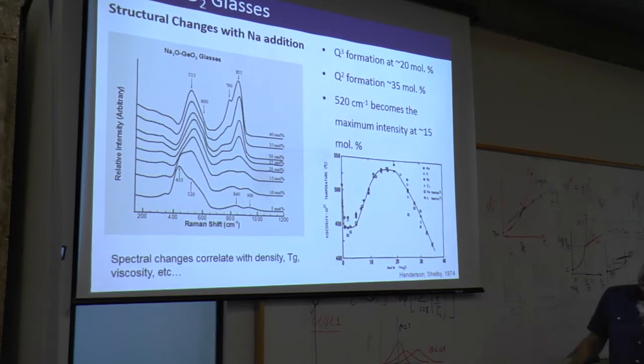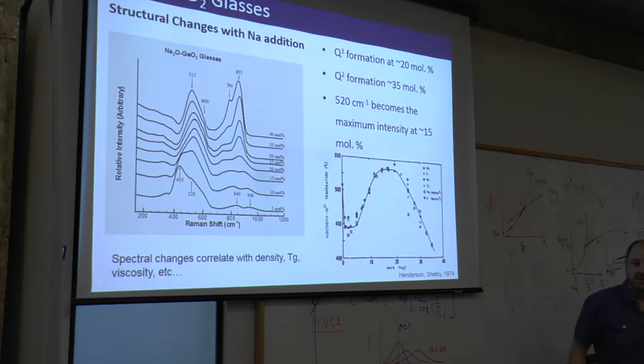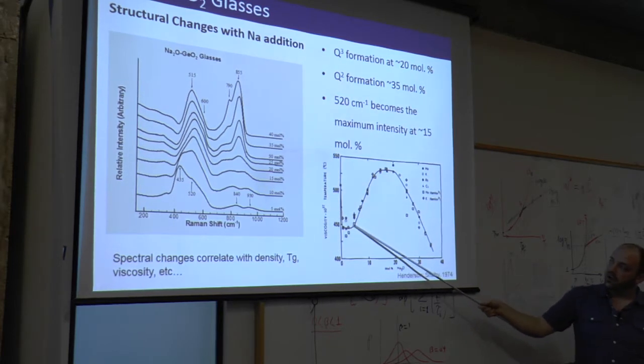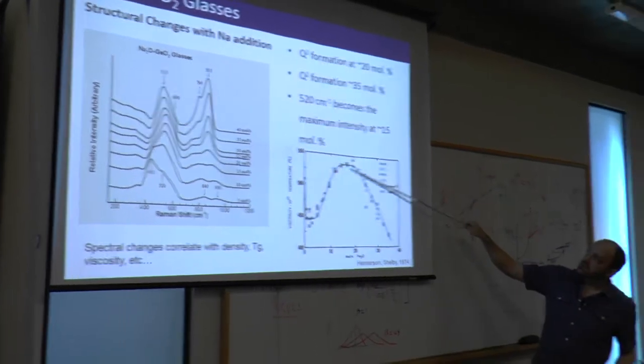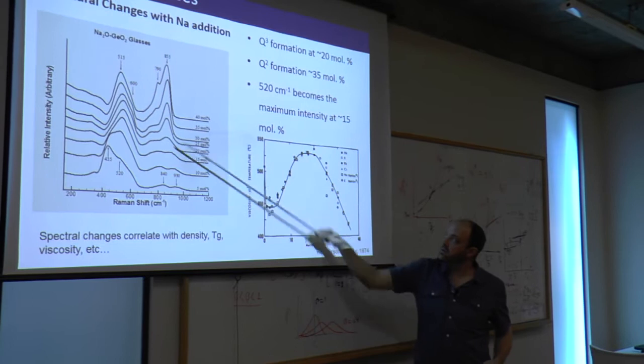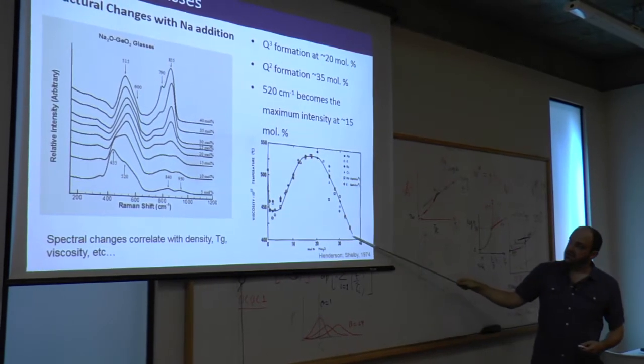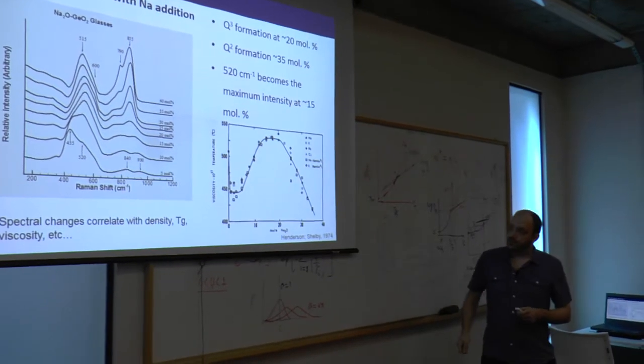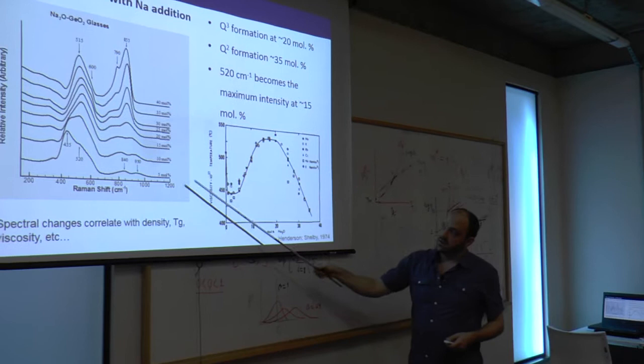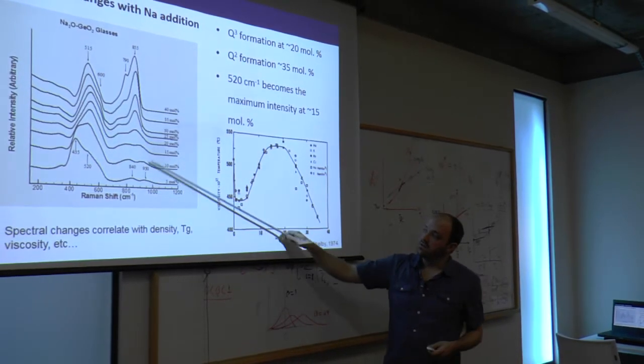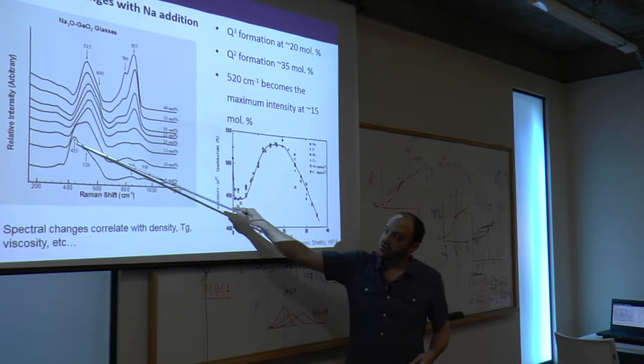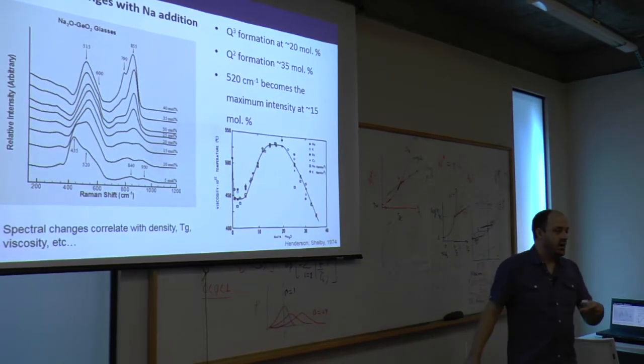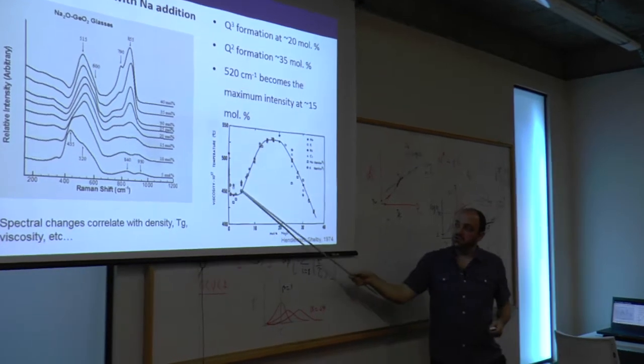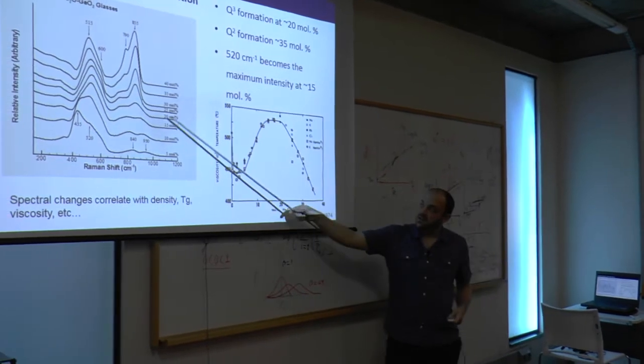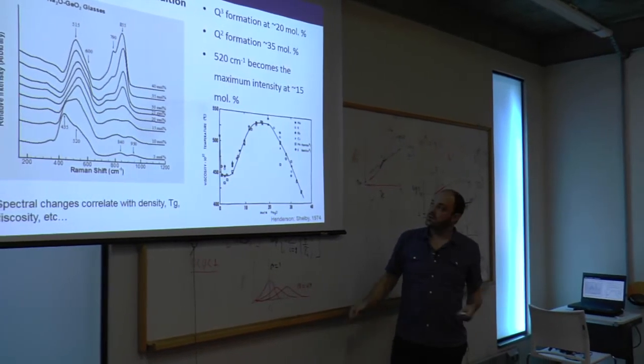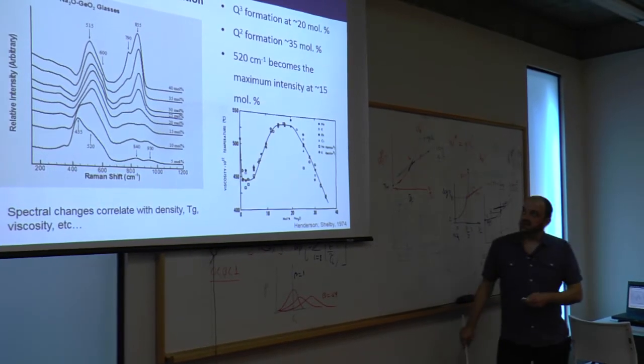If we look at some of the properties, these changes actually correlate with Tg, density, viscosity, and here's just one example. But we see almost no change, and then quite a rapid change to a maximum around 20% here, where we really start to break down the germanate network, and then it decreases again as you increase the sodium content. So what's happening here, or at least I think this is the accepted interpretation, is that as you add sodium, you're actually changing the germanium from tetrahedral to octahedral. And so as the germanium changes, you don't get much change in the network. Whereas once you really start to break down the network and form Q3s in these lower Qn species, you have quite dramatic changes in the viscosity.